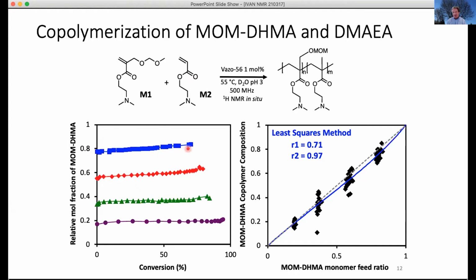And now as we go through the copolymerizations at different ratios of M1 and M2, the composition does not drift. So now polymer formed early and formed late during the 8-hour polymerization has exactly the same composition. And that's reflected in reactivity ratios. If they approach 1 and 1, it means they really want to copolymerize in a purely statistical fashion.